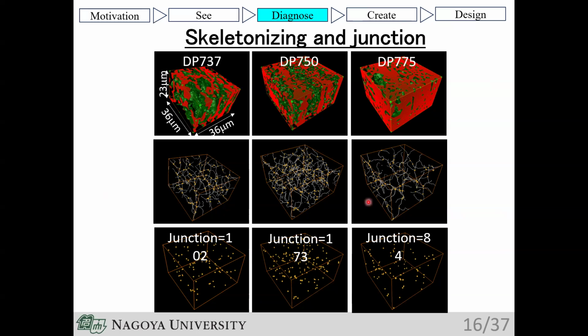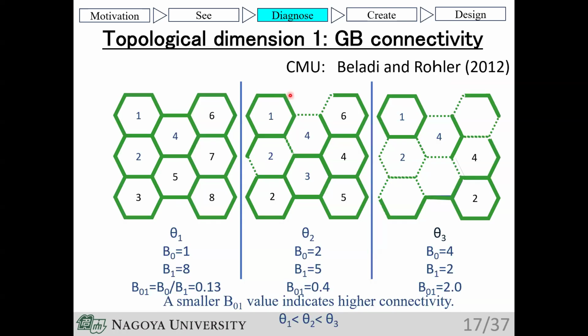The number of nodes, the branching points, serves as a quantitative measure of the entanglement. For instance, the branching density reaches a max at the intermediate annealing temperature, the intercritical annealing temperature, providing a structural basis for understanding the strength-ductility balance. Also, this is very useful to characterize grain boundary characters.